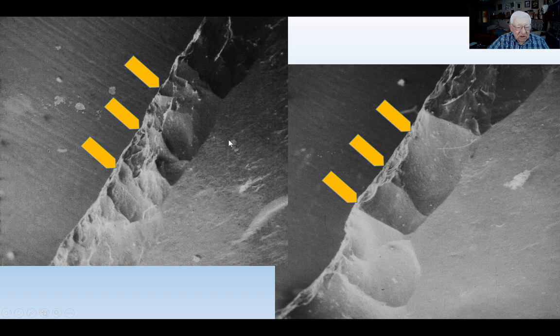because the internal structure of flints is well seen if one has practice, and one may say the direction of growing of chalcedonic crystals. And the best direction of knapping is parallel to the internal structure, this means to the orientation of growing, recrystallizing chalcedony crystals.